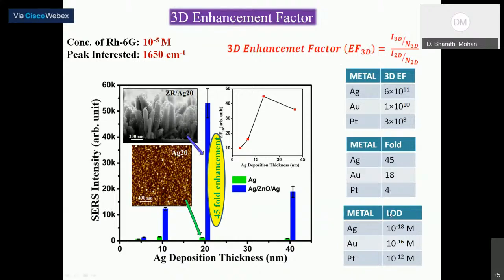And the limit of detection has been calculated for all three different hybrid structures. And in case of silver, we achieved LOD of about 10 power minus 18 molarity, whereas in case of gold and platinum, it is about 10 power minus 16 and minus 12 molarity respectively. So the silver-based hybrid structure gives the maximum enhancement and better LOD.